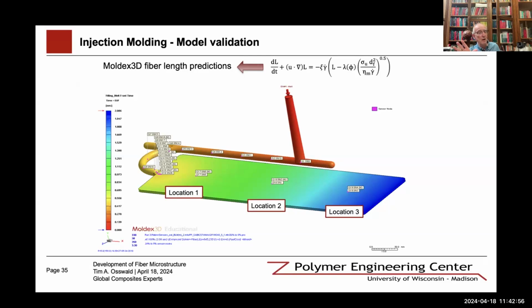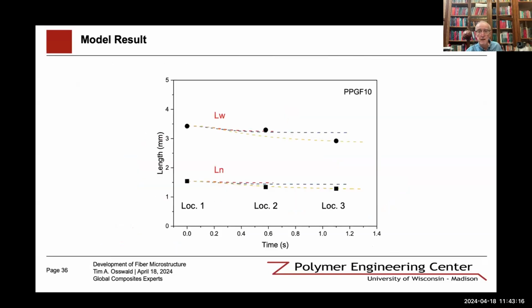So here, what we need to remember is we start out with fibers that are 15 millimeters long, and so we still don't have a model that can actually predict what occurs during the plasticating unit. And you'll see later that it's a more complicated issue. But if we have the purged length distribution, we can basically very well predict the fiber length distribution at the three locations, the number average and the length average throughout the plate. And you can see for different parameters in the model from Tina's work, we can actually fairly accurately predict that.